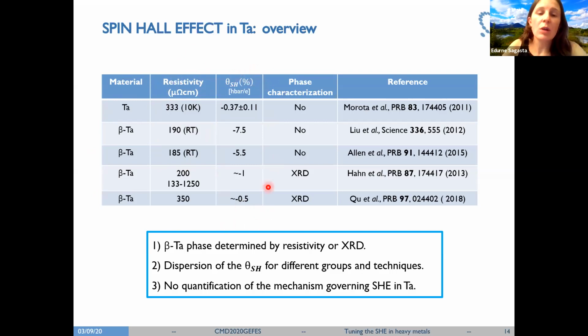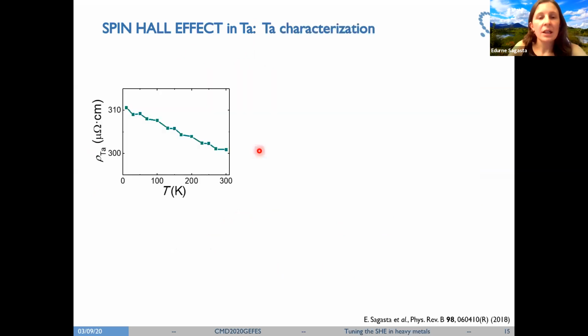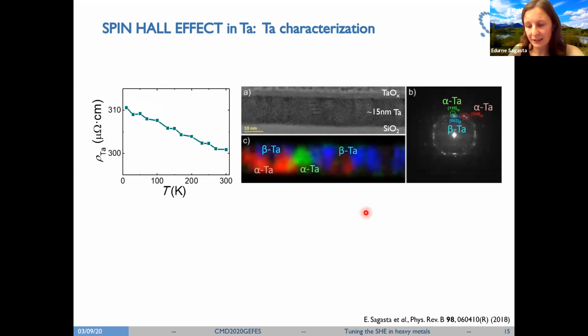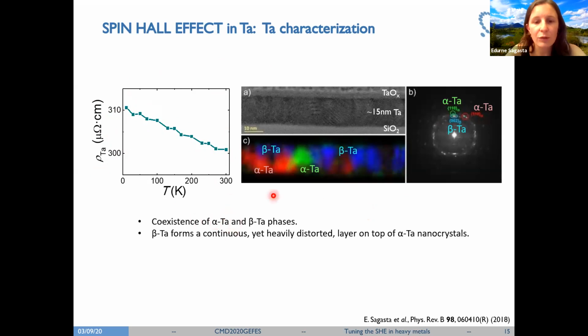We can also see some dispersion in the spin Hall angle value from group to group and technique to technique. And experimentally, there is no quantification of which mechanism is governing the spin Hall effect in tantalum. So in order to investigate more on this, we have performed again the spin absorption experiment by using lateral spin valves where now the nanowire, the spin-orbit metal, will be made of tantalum. And here we can see the resistivity of the tantalum. This curve shows that the resistivity is characterized by a negative temperature coefficient, and the variation of the resistivity with the temperature is very narrow. This corresponds with beta tantalum, but we decided to make the phase characterization by doing a transmission electron microscopy experiment. And what we saw is that we have the coexistence of alpha and beta tantalum phases. Importantly, the beta phase is the one that is on the top.